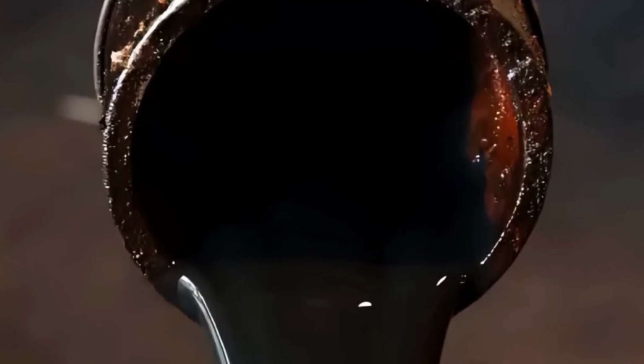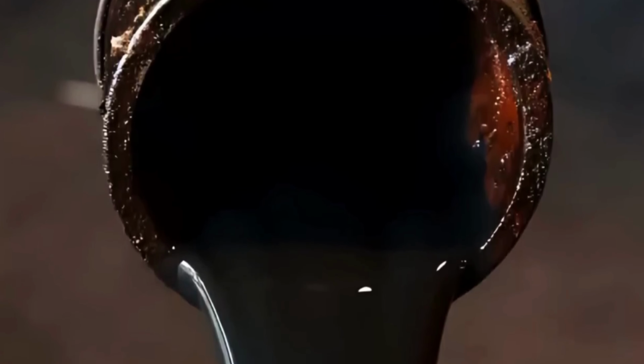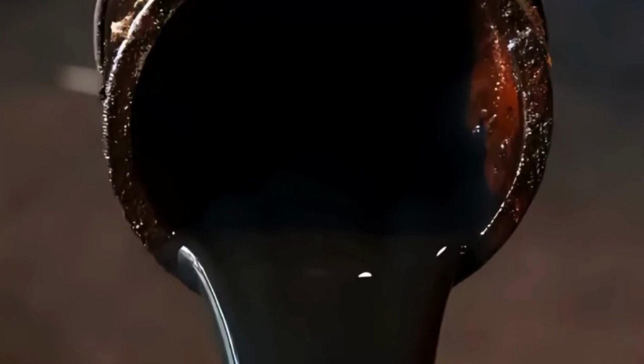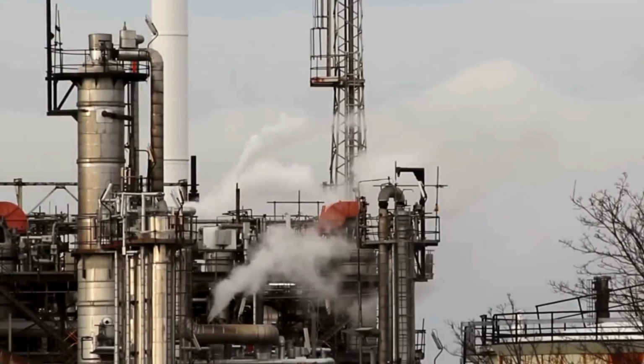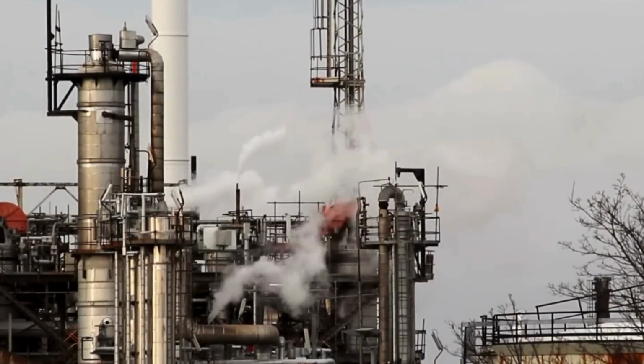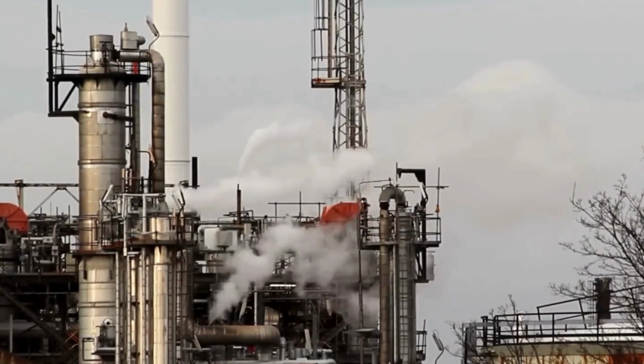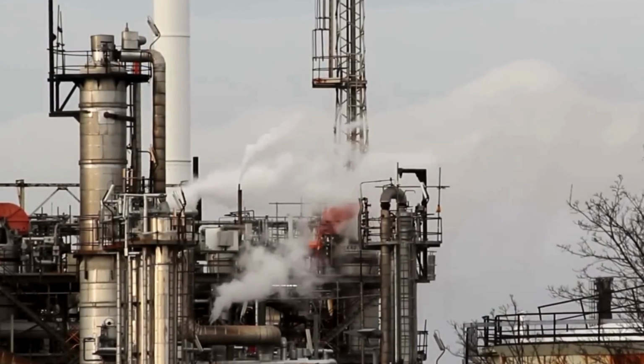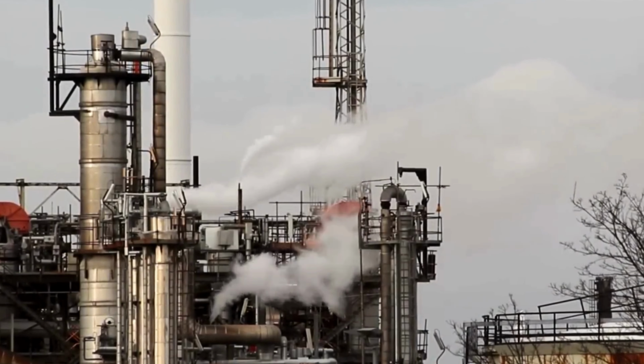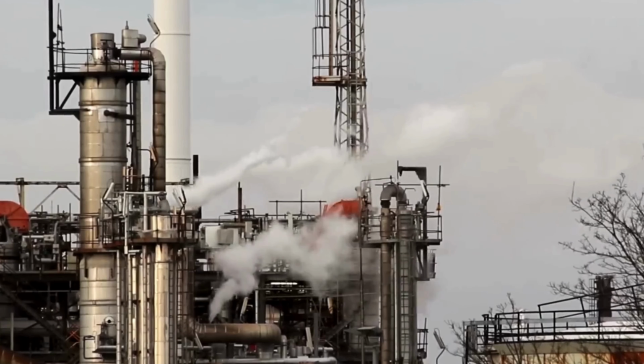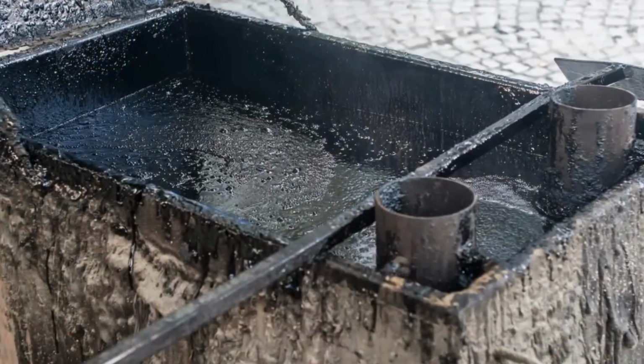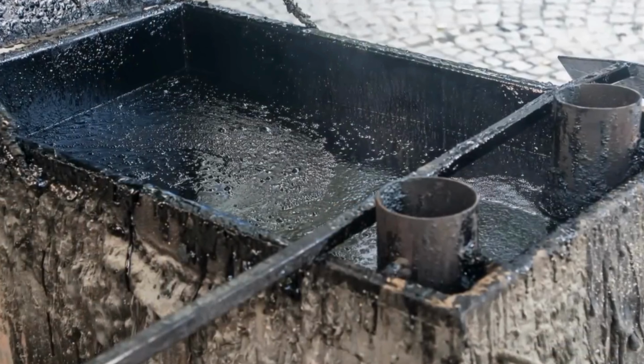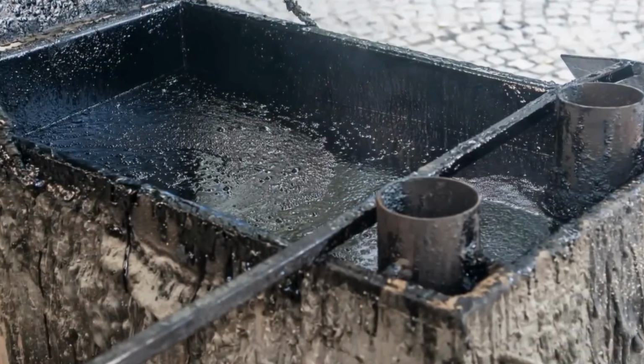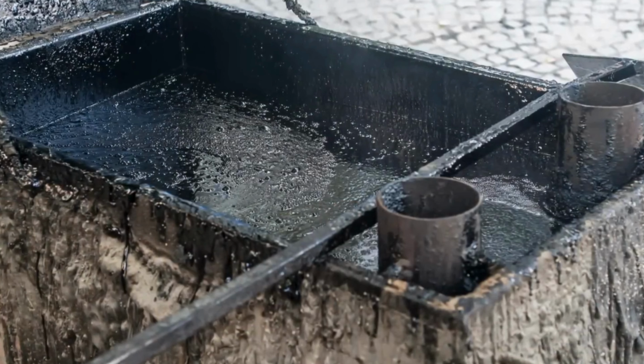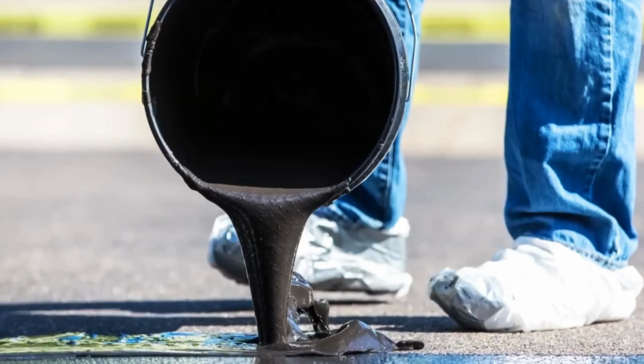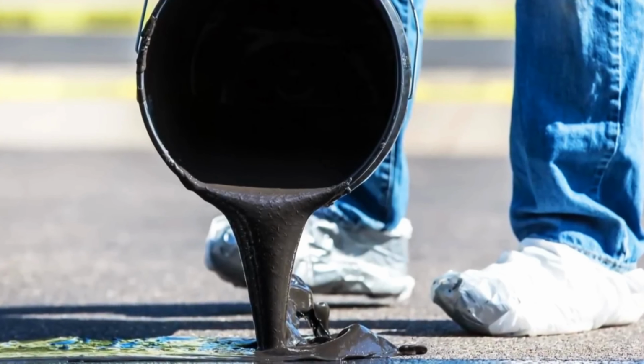This bottom residue still contains valuable components, so it undergoes further separation using vacuum distillation. Vacuum distillation works by lowering pressure inside the tower, allowing heavy oils to boil at lower temperatures without cracking or burning. The residue is reheated and fed into a vacuum tower. Under reduced pressure, more usable gas oils can be extracted, leaving behind an even heavier material known as vacuum residue. This vacuum residue is the base for road-grade bitumen in many refineries.